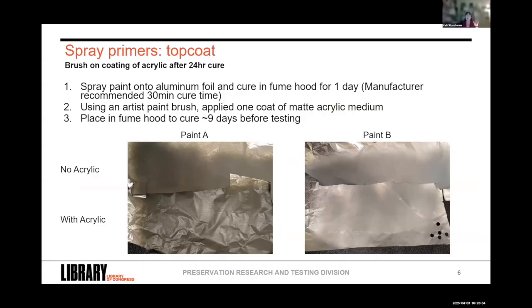A potential solution that was proposed was putting an acrylic top coat over the spray paints. So I'll go ahead and say the last data I was showing was after the paint's cured for about 10 days in a fume hood, so lots of airflow, and we're still getting all of that. Manufacturer on the spray cans were saying 30 minutes of cure time. But to do these top coats, I only let them cure a day, still above that manufacturer time, before just applying some matte acrylic medium over top.